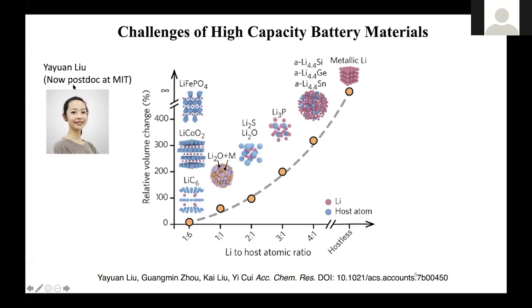What I list right here, if you look at the vertical axis, is the relative volume change. The horizontal axis is the amount of lithium you store versus the host atomic ratio. And for the past 40 years, we have been playing with lithium iron phosphate, lithium cobalt oxide, graphite. And the lithium to the host atom is roughly 1 to 6 to the left of this plot. And with more and more energy put in, you need to put more and more lithium ions going in. And so the amount of volume change will go up tremendously. And these create huge problems for us to handle. How do we solve this problem?